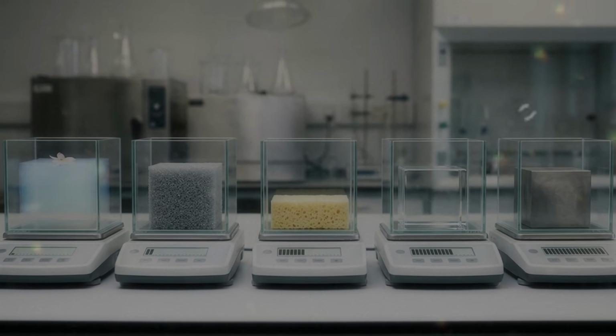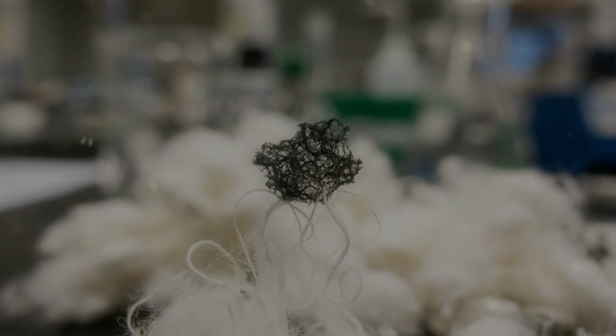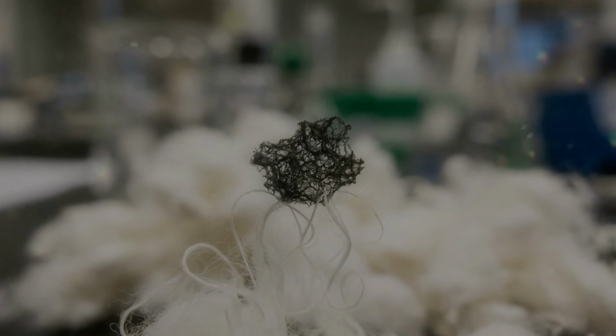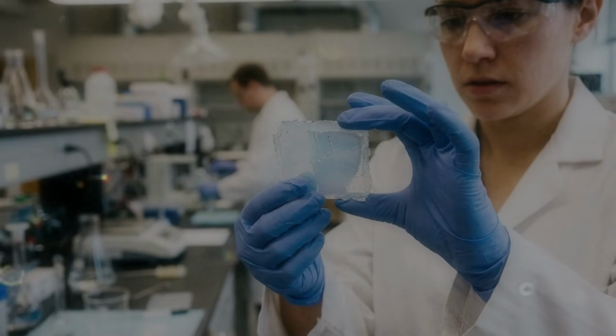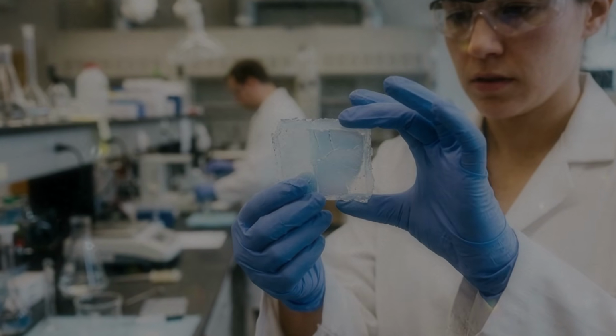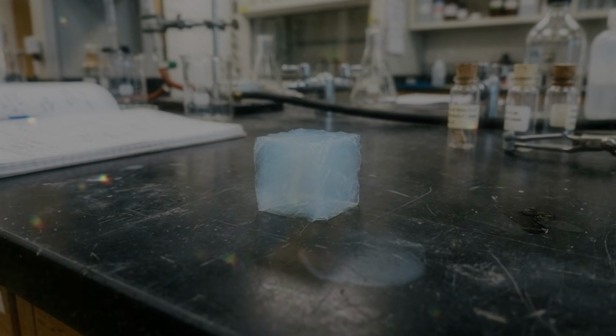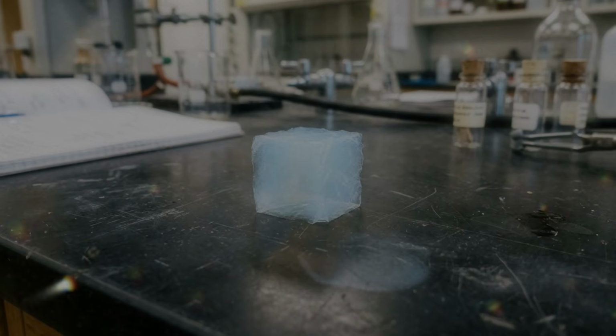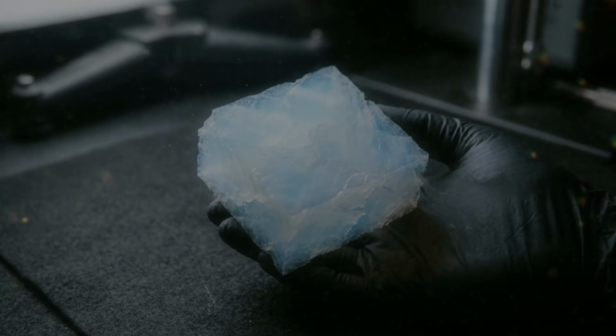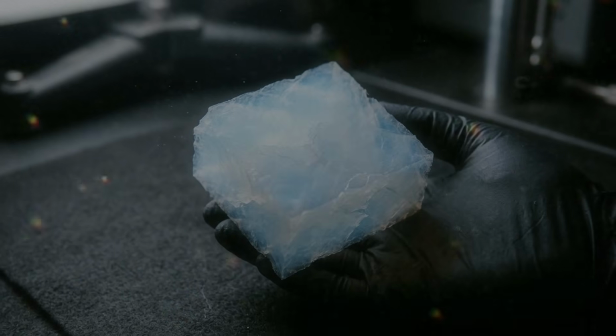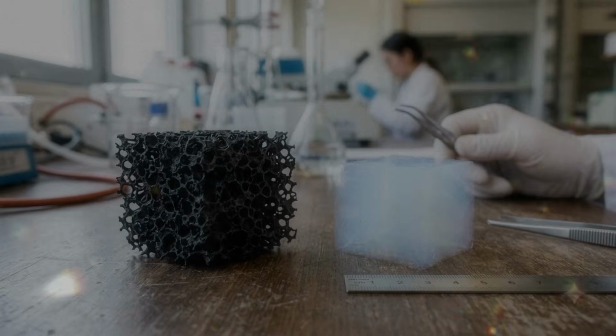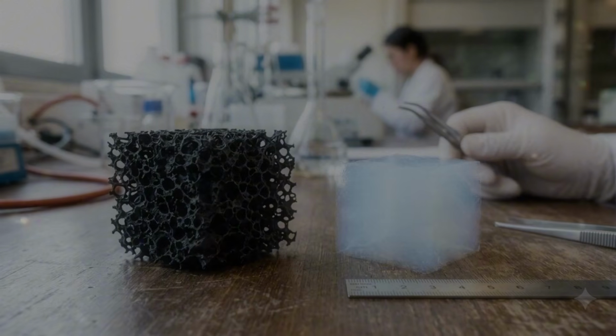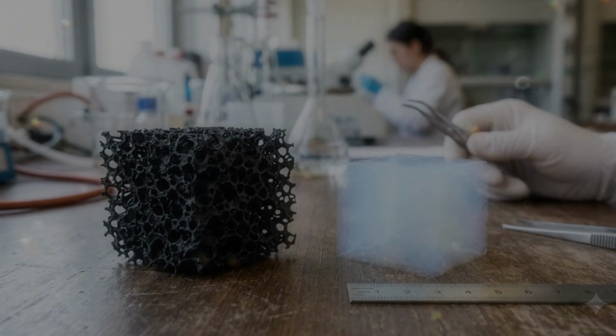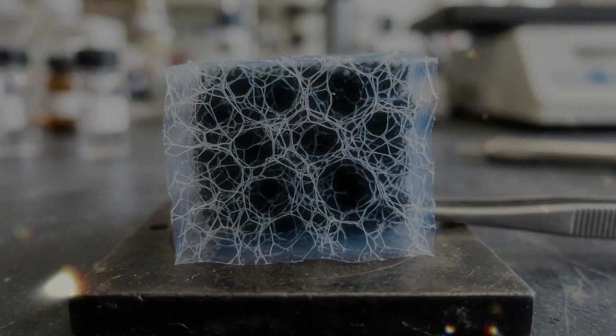This allows the finished aerogel to gain strength or perform an additional function. Once the network has formed, the wet gel often needs time to age. Aging sounds peaceful, and in this case it usually means allowing the structure to become stronger before drying begins. Chemical reactions continue inside the gel. New connections form between neighbouring particles. Thin branches may thicken slightly. Weak regions can become more stable. A newly formed gel can be surprisingly delicate. It may hold together, but only just. Moving it too quickly, exposing it to the wrong liquid, or allowing it to dry at the surface can cause cracks. Aging gives the network a better chance of surviving what comes next.